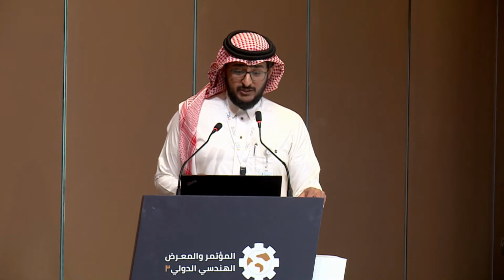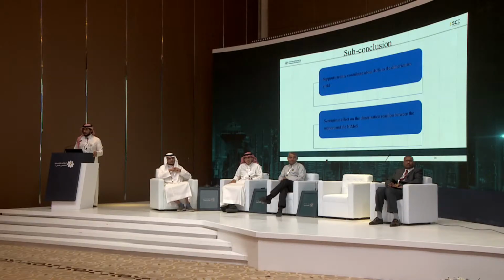Here is the comparison. We can see that at 1 millimole per gram of acidity, we have only 4 weight percent of dimers, and when we go to the sulfided or supported catalyst, we get around 10 weight percent. So that's the difference between both of them. That tells us the following: the support acidity contributes around 40%, which means the acidity coming from the support is only 40%. And the rest is coming from where? From the NiMoS catalyst. And there is something called a synergistic effect between the support and NiMoS that causes this.